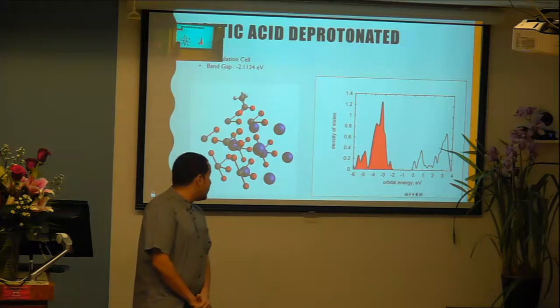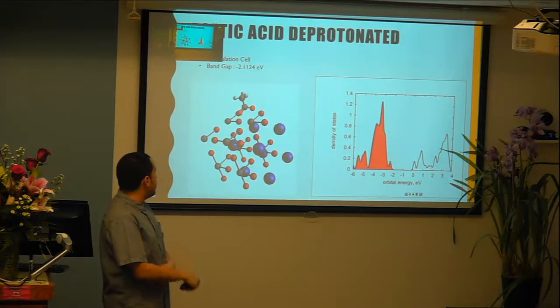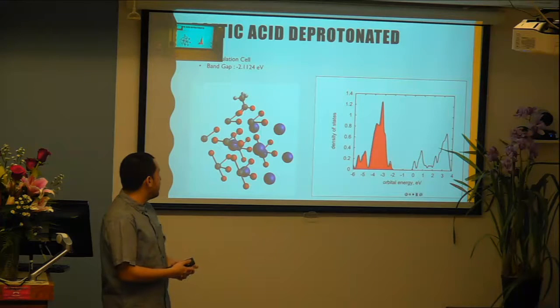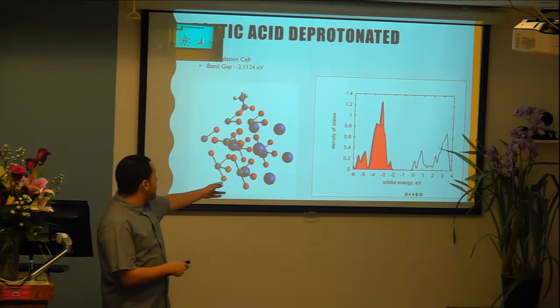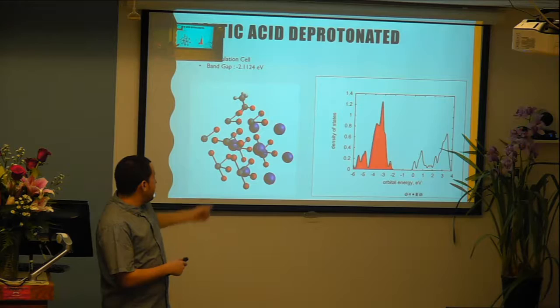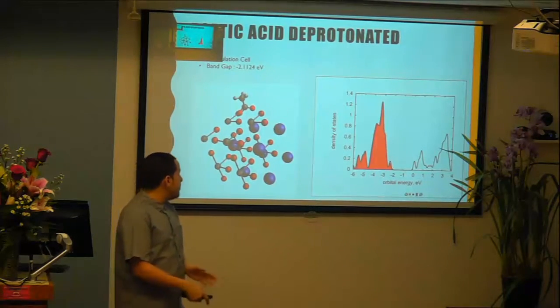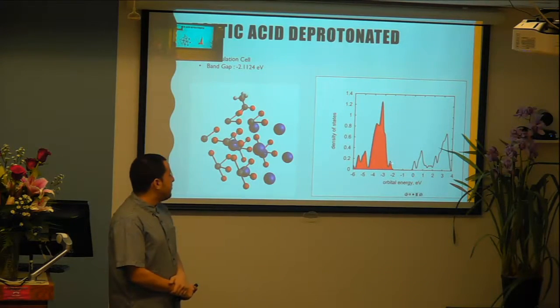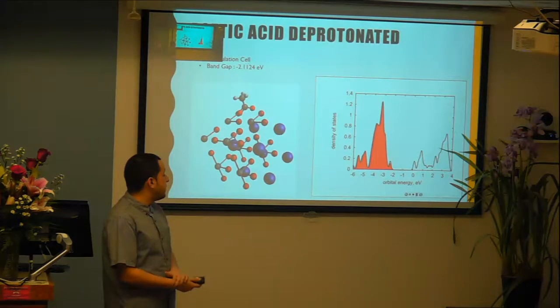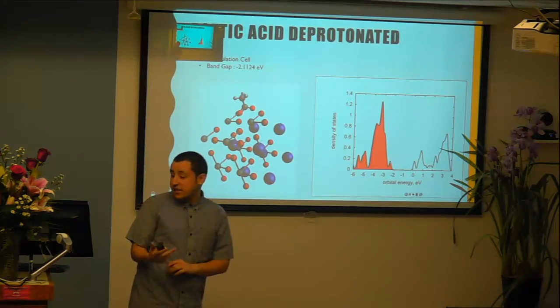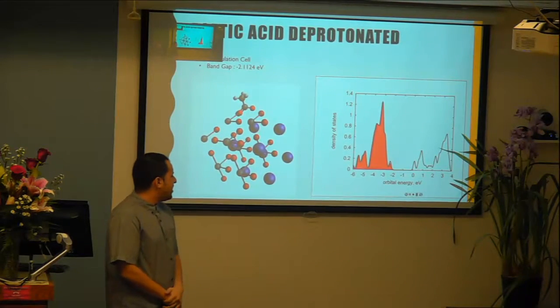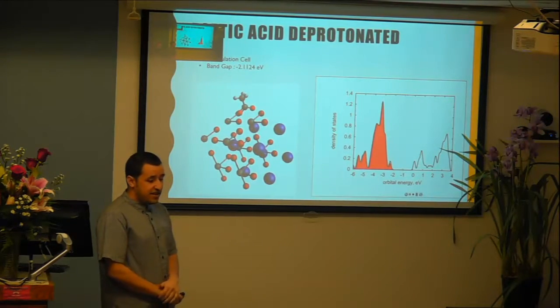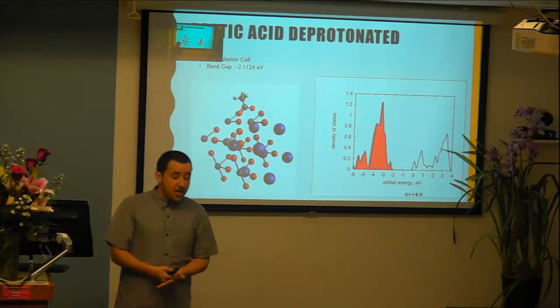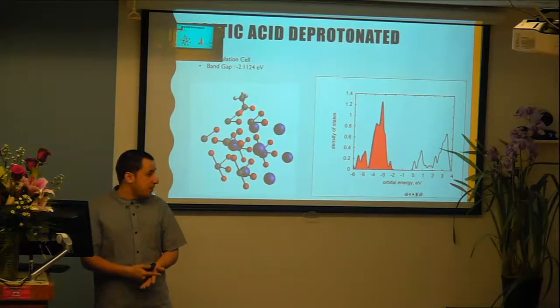So in this case, this is what my structure looked like. That's my 2D film. It's a 2x2x2 simulation cell with the acetate ion attached to the surface, with the purple being cesium, the gray being the lead, and the red being my bromide. So when I look at my density of states, I notice at about -2 electron volts that there's a little white space around the area. This is analogous to a p-type orbital. No, it's not a p-type orbital.